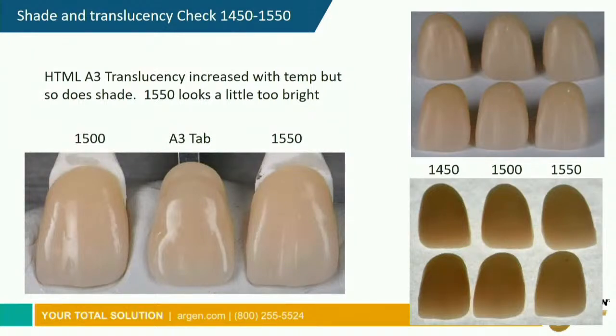So here we have a case where, as I mentioned, when you put the coloring oxides in there, the temperature matters, and the temperature that you fire it at could change the result. Here we have a 1500 degree and a 1550, and you see the 1550 is a little too bright compared to the tab as opposed to the 1500.